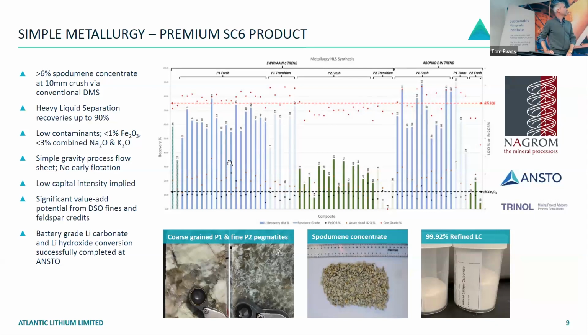And then from a metallurgical test work point of view, this is really important for any pegmatites. So you can see here, these are each composites down individual drill holes. There's 64 in total. The blues, dark and light, are our P1, dark being fresh and light being transitional or weathered material. And the greens are our P2 mineralization, again, dark fresh, and light weathered. And then I've split these up by those mineralization trends. So this block here is our Ewoyaa main trend, that north-south trend, the P1s, P2s, weathered and fresh. And this block here is our Abonku east-west trends, again, weathered and fresh. And you can see there are hardly any P2 samples. It's the overwhelmingly coarse-grained P1.